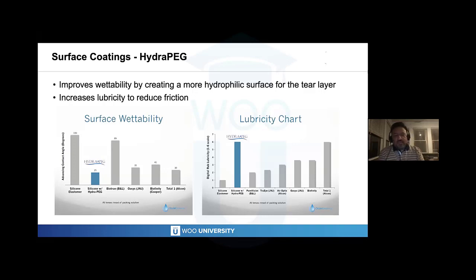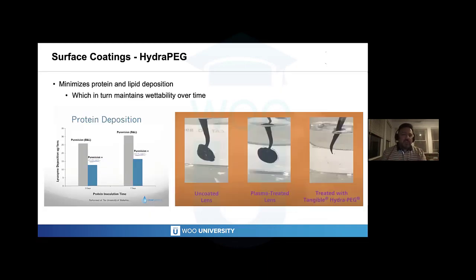Of the lens surface. And because of that, it also coincides that we also significantly improve lubricity. And of course, lubricity is the propensity of the lens to not create friction between the lid wiper and the eye. We talked about how important it was to keep the friction to a minimum. And again, the HydraPeg has a significant improvement in lubricity or reduction of friction between the lid wiper and the lens itself as that individual blinks. So no question at all that wettability and lubricity is significantly improved with that HydraPeg coating. What about depositing?